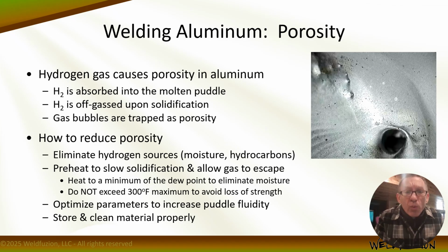Okay, now we jump to the Dynasty, which has the ability to focus the arc right down using higher AC frequency output. It forms a puddle faster, right? A lot of people have commented on that. Wow, when I switched to an inverter, I hit the arc and boom, the puddle was formed right away. Well, what we saw was that it didn't preheat the material around, so we got faster solidification rates if welding was to begin right away, like we were using visual indicators with our Syncrowave machine, right? So solidification rate was much faster.